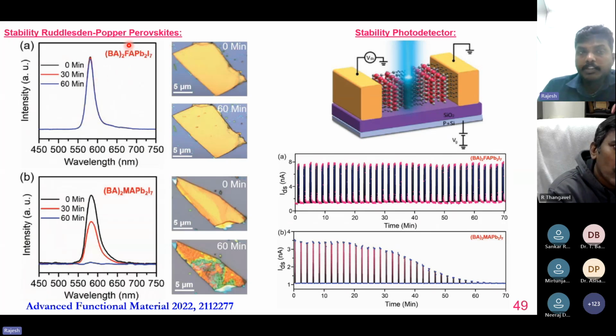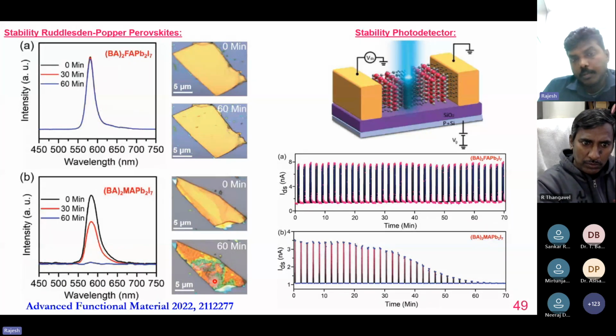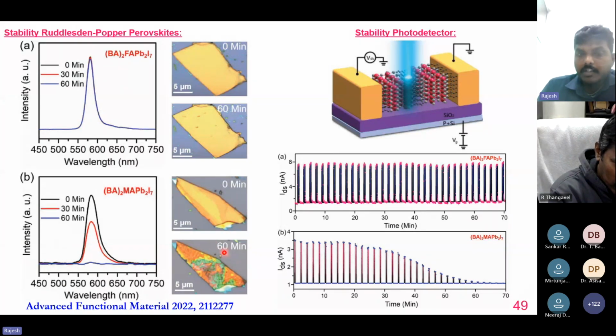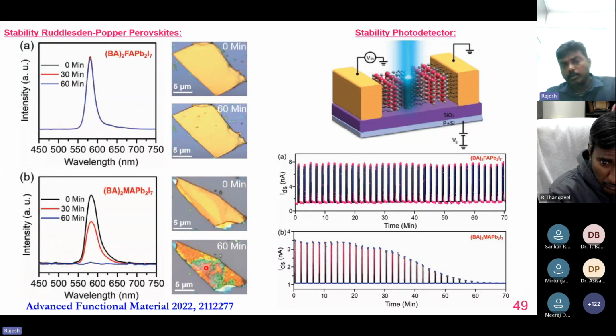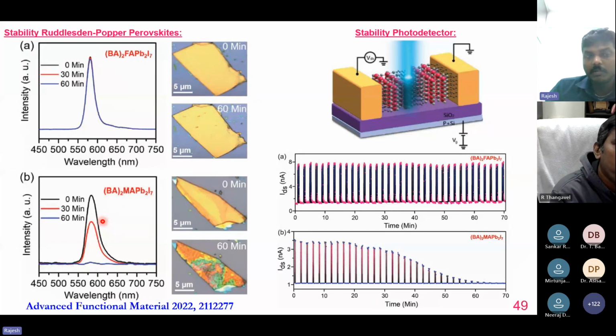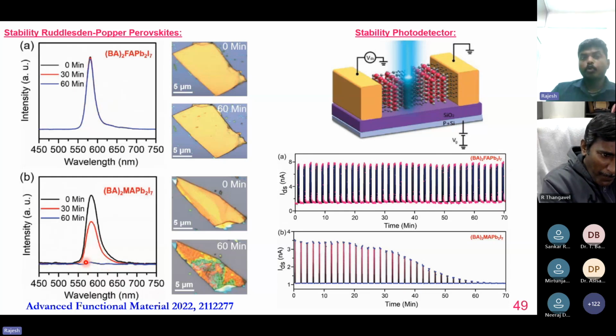In the presence of formamidinium, you can clearly see in the optical image there is no degradation, as compared with methylammonium based. In the methylammonium based, after almost 60 minutes of exposure to light, a lot of the layers are degraded. The same phenomenon we observed in the photoluminescence. In the case of 30 minutes, almost half the photoluminescence is gone. Then when it reached 1 hour, the photoluminescence is completely quenched. But in the case of formamidinium based perovskite, we are able to see good stability, with a very small amount of degradation.